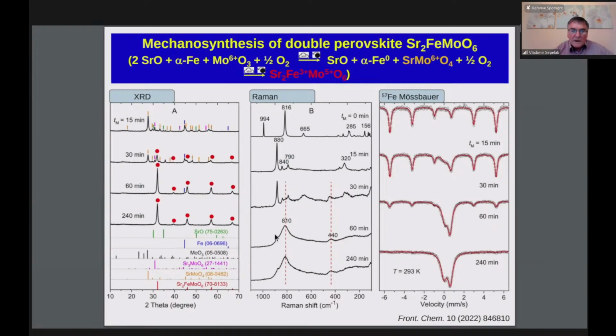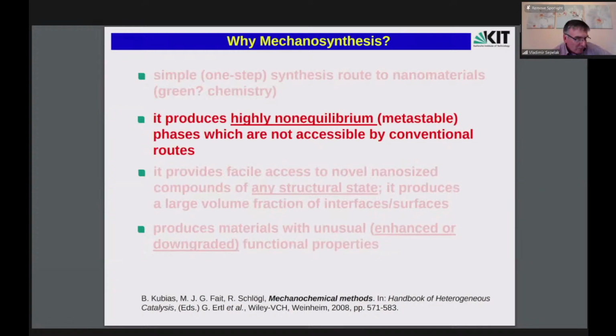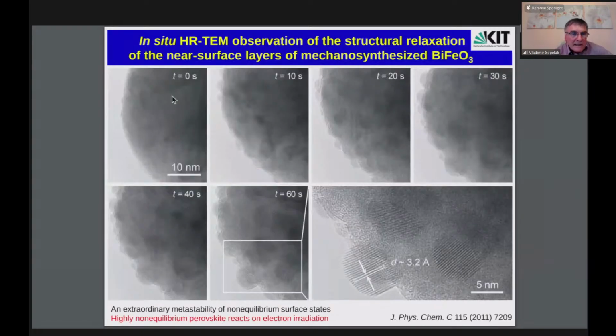240 minutes. The second important point of mechanosynthesis of complex oxides is that it produces highly non-equilibrium phases which are not accessible by conventional routes. This is also clearly demonstrated on this slide, where in situ high-resolution TEM observation of the structural relaxation of the near-surface layers of mechanosynthesized perovskite bismuth ferrite is presented. You see that, with observation time, even irradiation of the surface of this mechanosynthesized perovskite with electrons leads to crystallization and relaxation of this structural state.